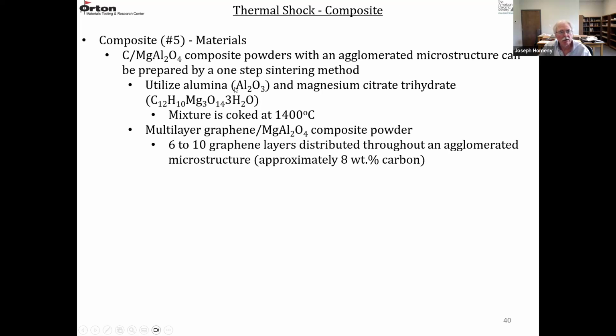So you start out with alumina, Al2O3, and a magnesium citrate trihydrate compound. So this is magnesium citrate trihydrate, C12H10Mg3O14, and then 3H2O. So in this combination, you have your source of aluminum, your source of carbon, your source of magnesium, and you also have oxygen. So you have everything needed to make this composite powder. So this mixture is cooked at 1400 degrees C.